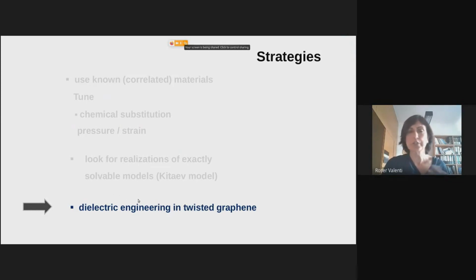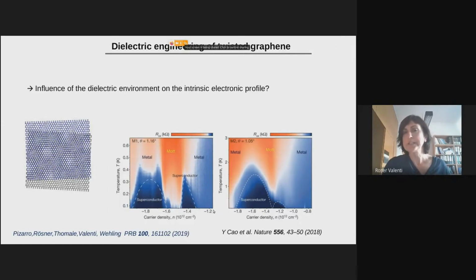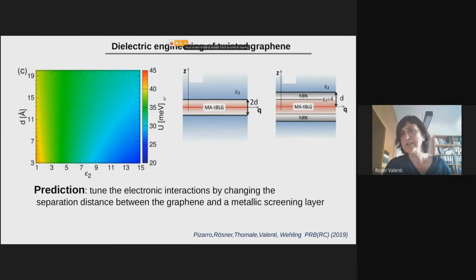The dielectric engineering was just work that we have been doing for these bilayer materials in order to be able to control the correlations in the system by making use of the distance. If this is your bilayer twisted graphene, and here is where the metallic plates are put, of course, one can change the dielectric environment by changing the distance of these metallic planes. So here it's distance with respect to the value of the dielectric constant, and this shows how strong the correlation is going to be. So for instance, by putting ourselves here, you see that correlations increase if you separate the distance between your bilayer and the metallic layers.